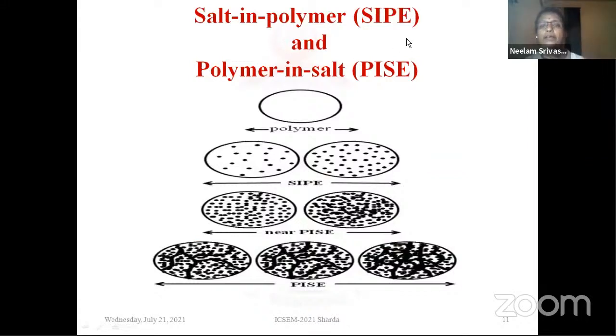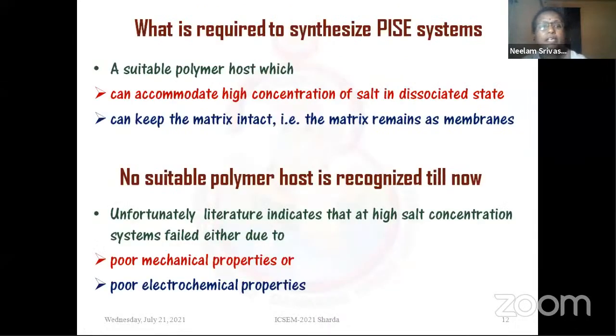One is salt in polymer electrolyte, and the other one is the polymer in salt electrolyte, which you can understand from this figure. If we start with the polymer and we start putting the salt till this near PISE system, where the cluster threshold is not achieved throughout, till then the ion transport will be through polymer segmental motion. And once the threshold has been achieved, the ion transport will be through the ion matrix. So it divides the whole polymer electrolyte into two parts, where the salt concentration is low, and the other one where the salt concentration is high.